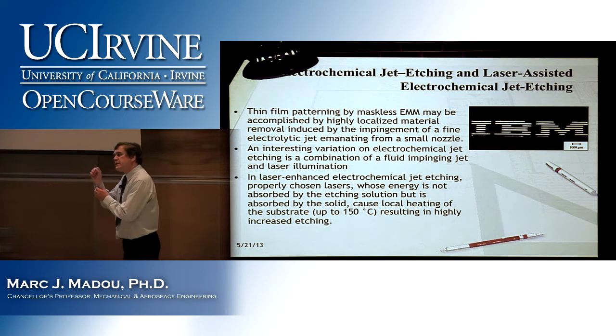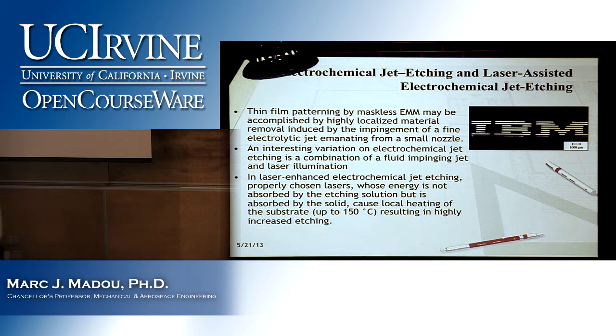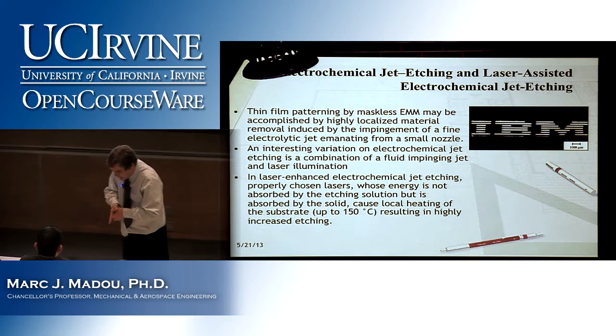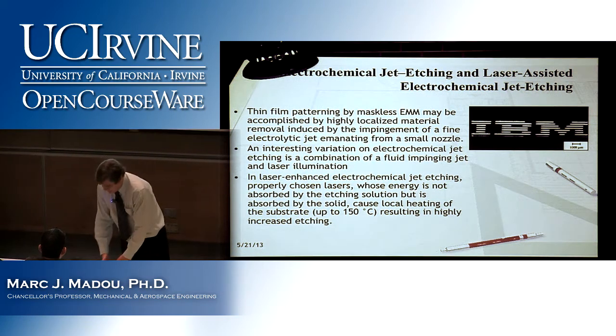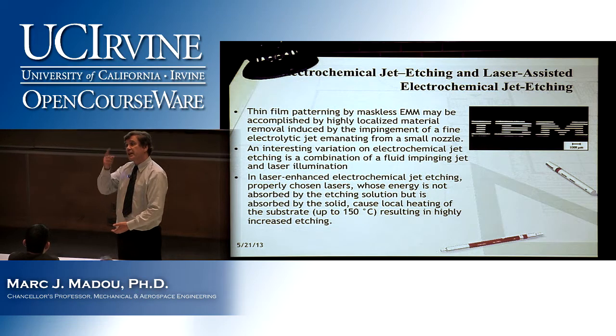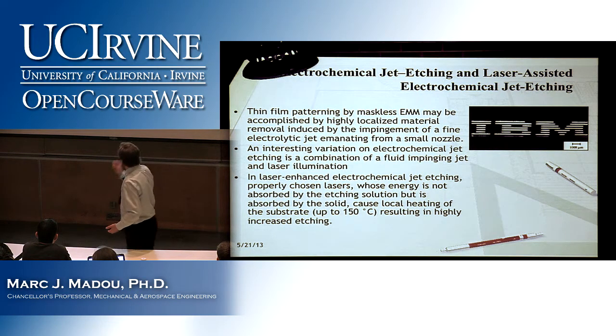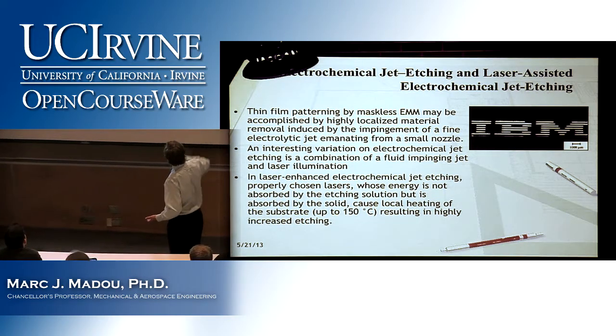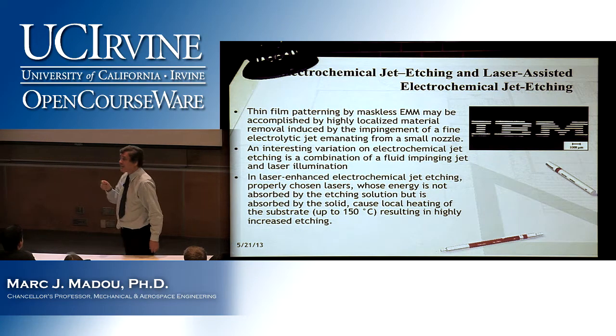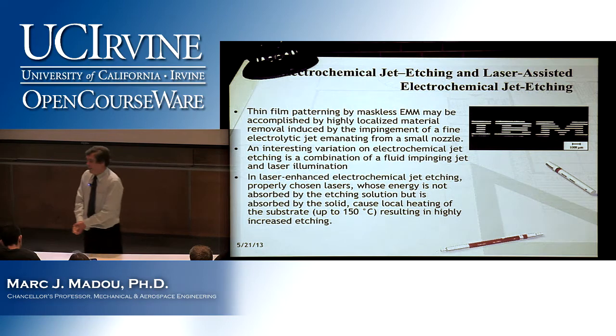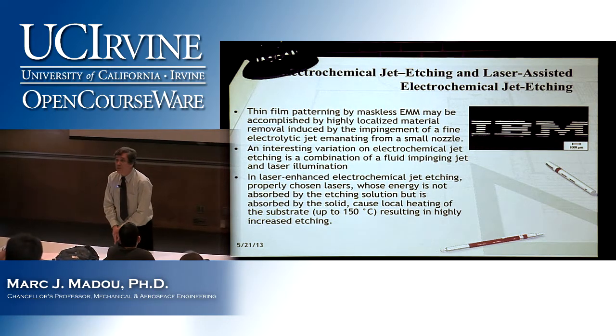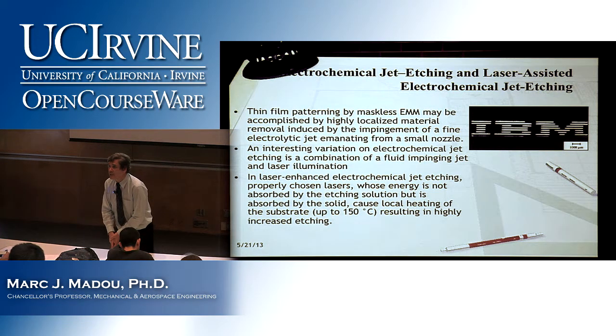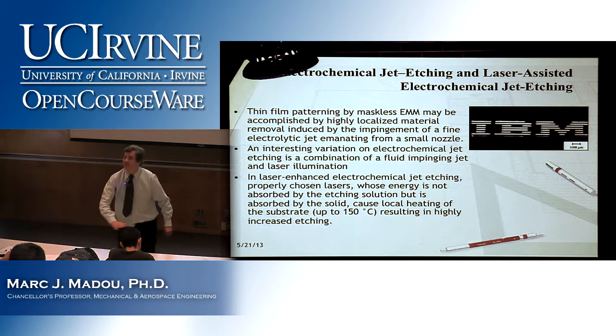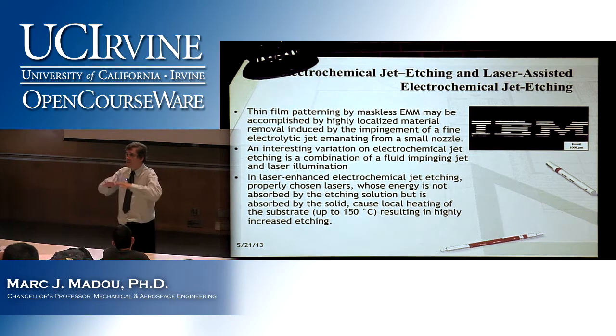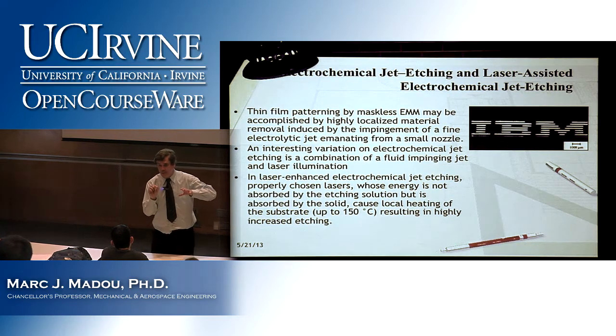Both have to do with using jets of an electrolyte. If I have, let's say, this metal piece, and I have a jet of impinging liquid on this metal, I can still do electrochemistry, but I define the electrochemistry by the size of the nozzle. In this case, this IBM logo, and you can see the dimension, 1,000 microns, is really written by jet electrochemical machining. Think about your inkjet printer nozzle. You use that to eject a stream of liquid, and that stream will only corrode the metal away where it has hit the material. Of course, you could say that liquid will spread out. You need a mask, right? So you put a mask over it, and then the electrochemistry will only happen in the holes of the mask.